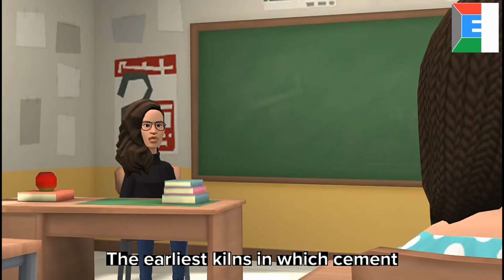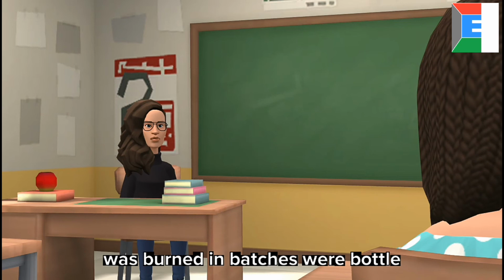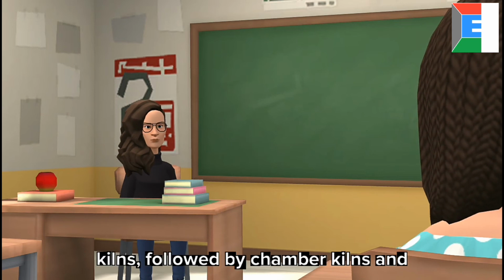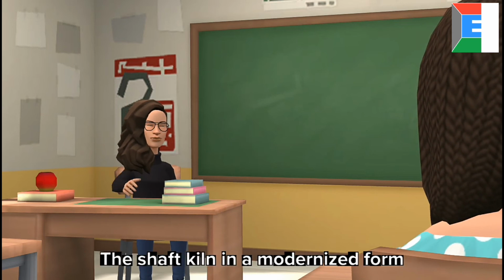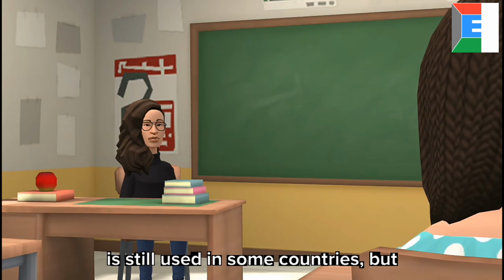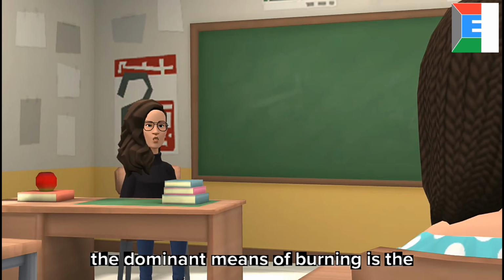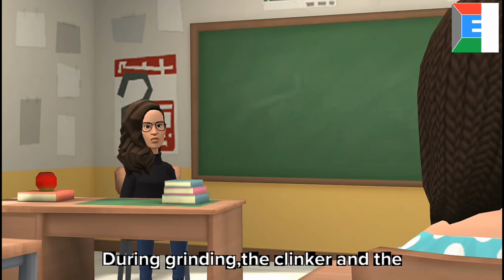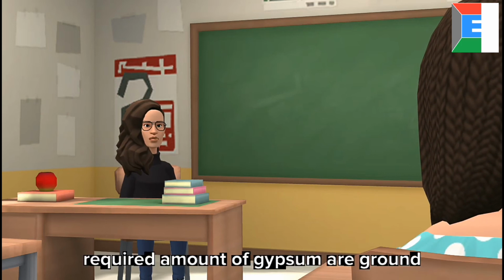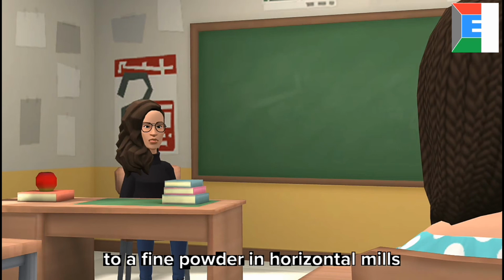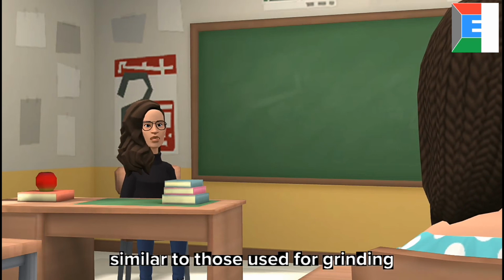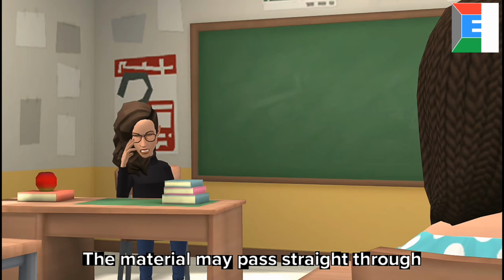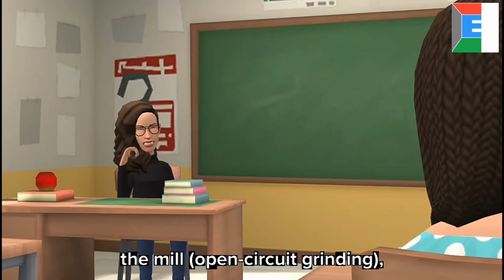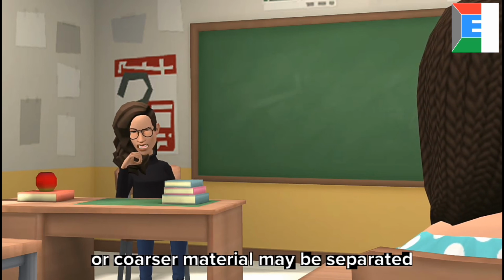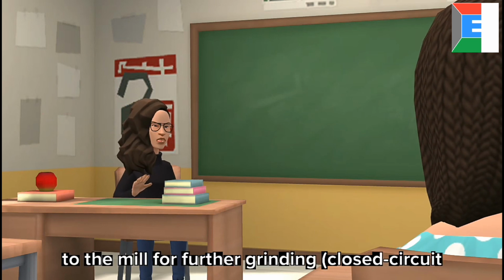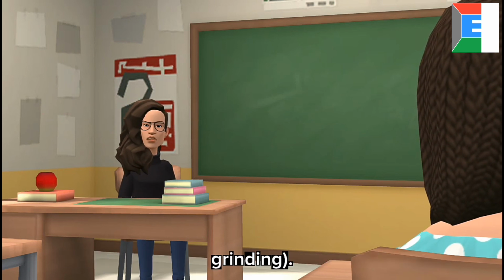The earliest kilns in which cement was burned in batches were bottle kilns, followed by chamber kilns and then by continuous shaft kilns. The shaft kiln in a modernized form is still used in some countries, but the dominant means of burning is the rotary kiln. During grinding, the clinker and the required amount of gypsum are ground to a fine powder in horizontal mills similar to those used for grinding the raw materials. The material may pass straight through the mill, open circuit grinding, or coarser material may be separated from the ground product and returned to the mill for further grinding, closed circuit grinding.